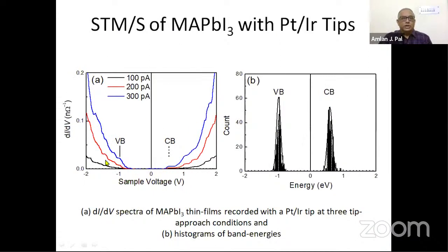We just get density of states, and we get a peak for the valence band and the conduction band. That is, we get the first peak where we can give an electron to the conduction band, or this peak tells me where I can withdraw an electron. So this STS measurement tells me the location of the conduction and valence band. Since it is an extremely localized mode of measurement, we do the measurements at many different points and plot a histogram of the two energies, and we finally get the conduction band and valence band. This is without any spin polarization, so I get only one conduction band and one valence band.